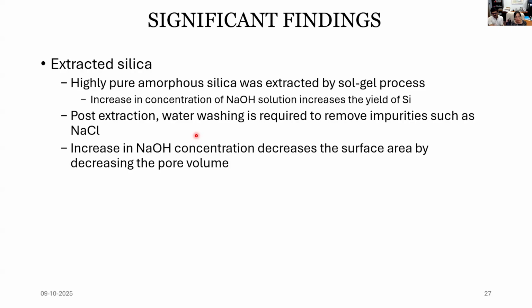And post extraction of the silica, it's mandatory to wash this material with water in order to remove any impurities such as sodium chloride from the system. Also, when we use higher sodium hydroxide concentration during this extraction process, it actually decreases the surface area of the system by decreasing the pore volume.